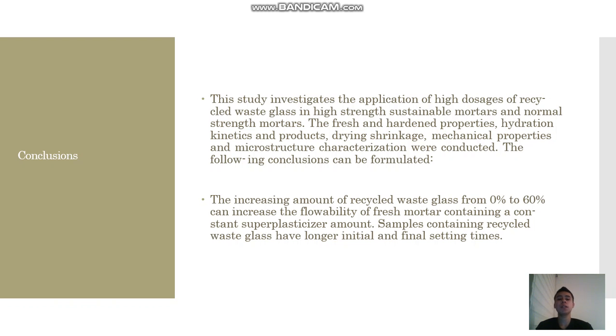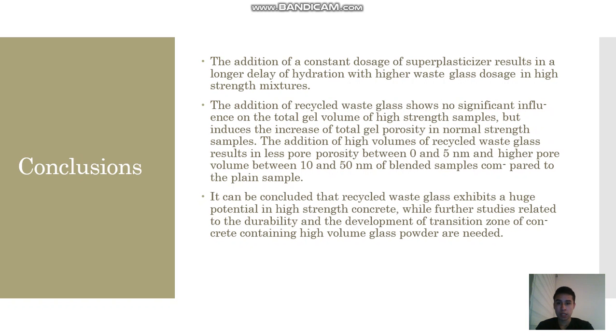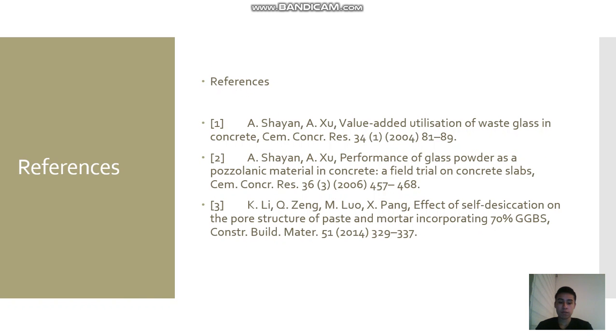The fresh and hardened properties, hydration kinetics and products, drying shrinkage, mechanical properties, and microstructure characterization were conducted. The following conclusions are formulated. The increased amount of recycled waste glass from 0% to 60% can increase the fluidity of fresh mortar containing superplasticizer. The addition of a constant dosage of superplasticizer resulted in a longer delay duration. We highlight the glass dosage in high strength mixtures. Reference. Thanks.